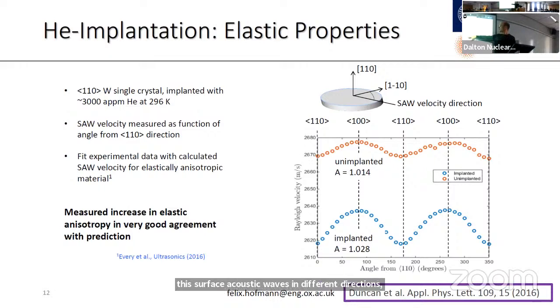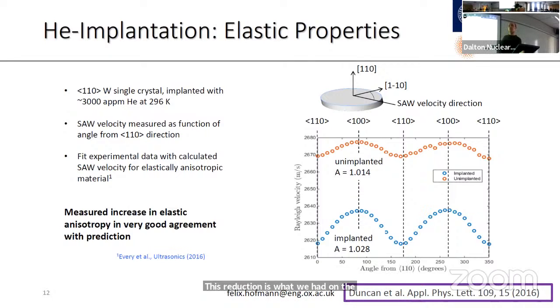And what you see up here is the data now, surface acoustic wave velocity for a tungsten sample with 110 out of plane direction, and we're then measuring different directions in the plane. This is how surface acoustic wave velocity varies in the unimplanted part of that sample. Down here, what you see is the implanted part. This reduction is what we had on the previous slide, 2% on average. And you can also see that the anisotropy has gone up to about 1.03. We predicted 1.02. So again, it's reasonable. We were really happy when we measured this because it meant that we weren't entirely wrong the first time around. And this was about a year and a half after the previous work.